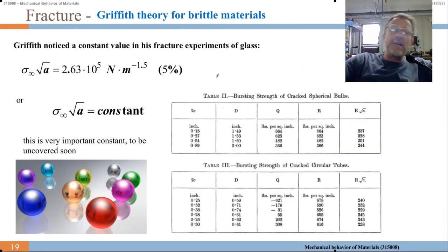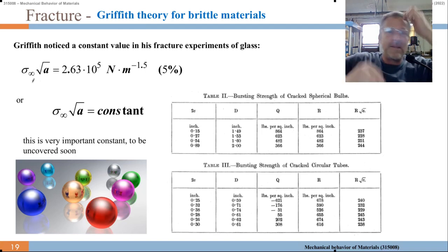So he noticed a constant value in his fracture experiments of glass, namely sigma infinity, the applied stress at infinity, not at the stress concentration, times the square root of A or C, is 2.6 times 10 to the 5 Newton per square root meter to the minus 1.5. I wanted this unit because sigma also is in Newton per square meter. This is within 5% error.